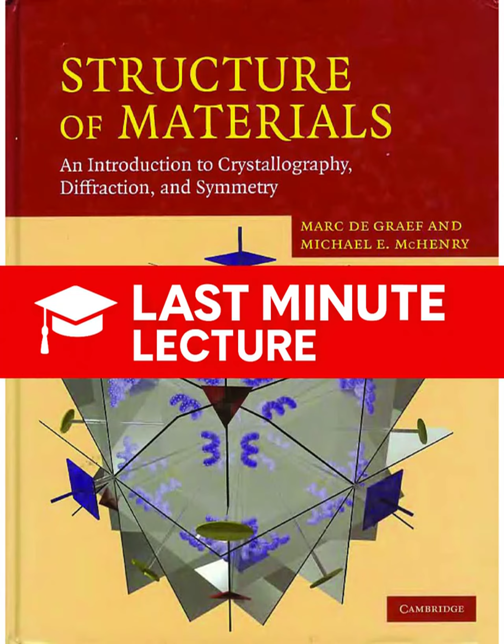We do. The silicon and aluminum tetrahedra link up in a pattern of 24 tetrahedra to form a complex polyhedral unit, a truncated octahedron. Which is basically a highly symmetric 14-sided figure where the corners are sliced off. Correct. And the key is that these cages are large internal voids. The sodium and chloride ions fill these voids. However, in sodalite, these cages are isolated. They are large, but they don't connect to form continuous channels. And this lack of interconnectedness is what distinguishes sodalite from our next example, zeolites.